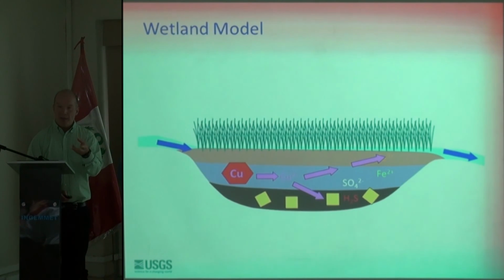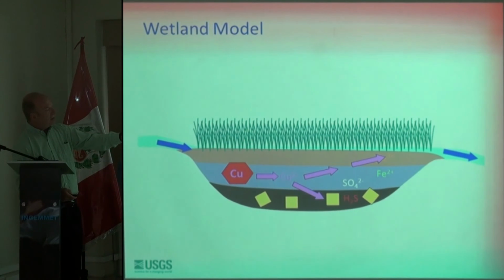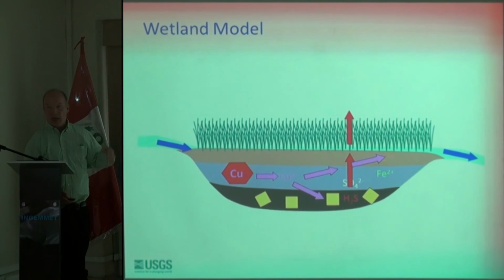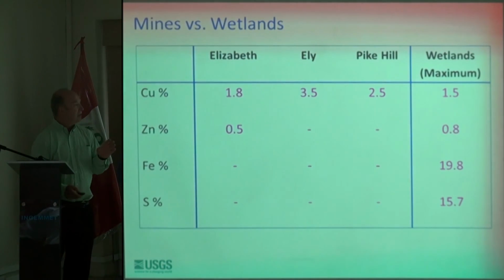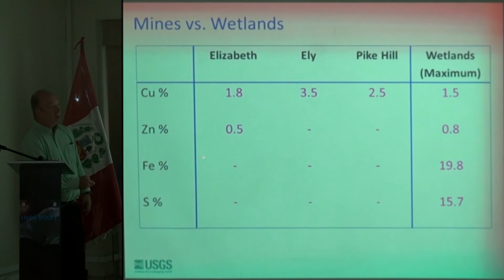Now, if you worry about what's happening with the sulfur in this system, because we've removed so much iron through neutralization upstream, there's no longer enough metal to consume all of the sulfur that is moving through the system. So that means some of the sulfide sulfur will combine with the metals, but then some of it also will either be lost as a gaseous phase to the atmosphere, or it could get reoxidized to sulfate and continue downstream.